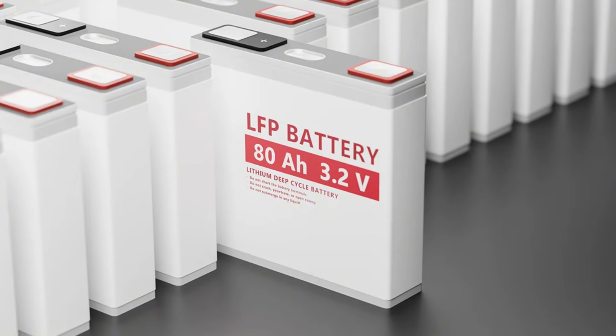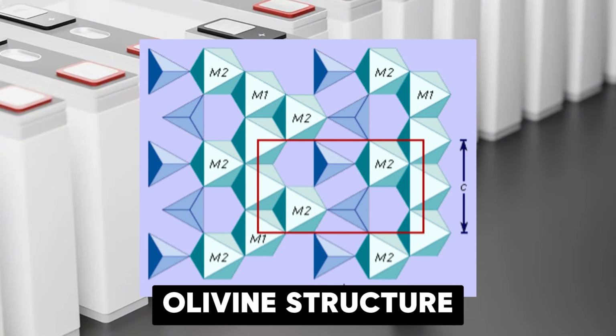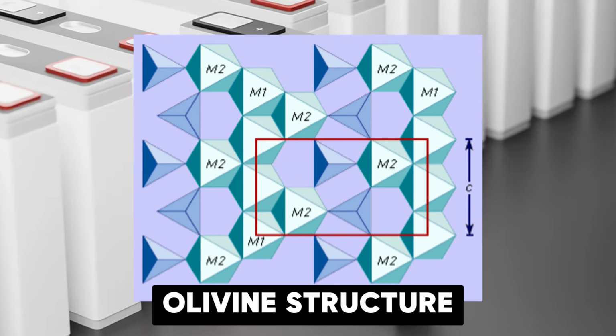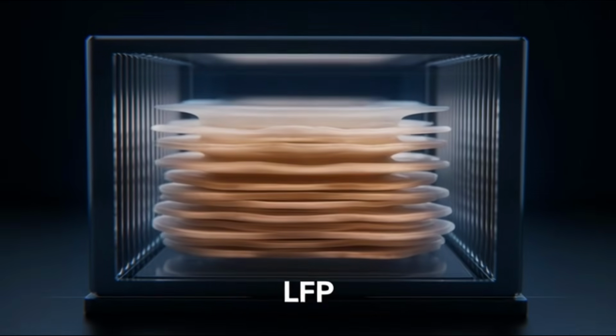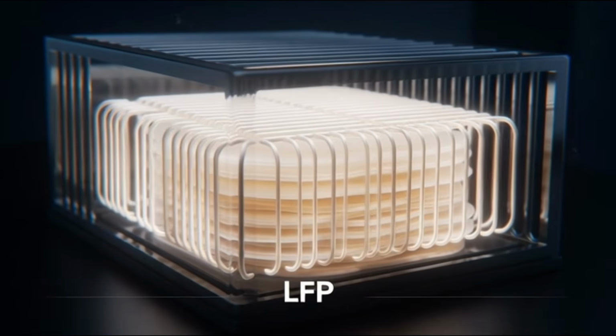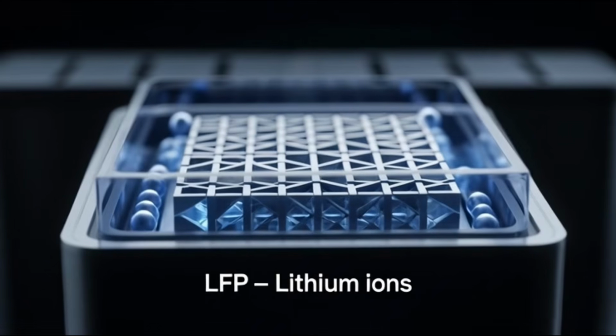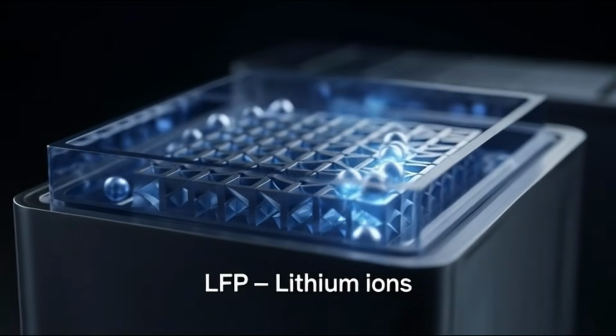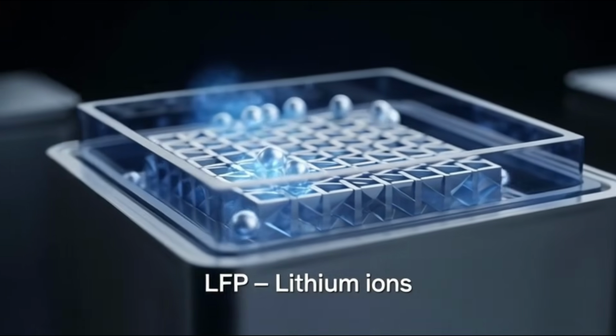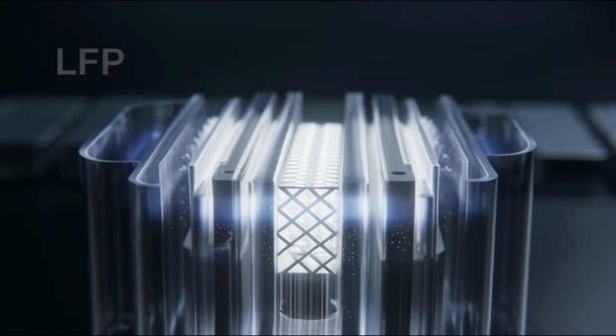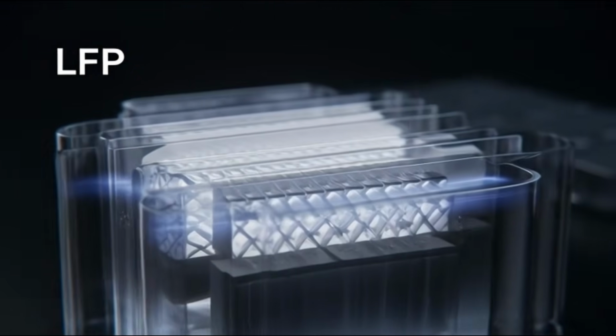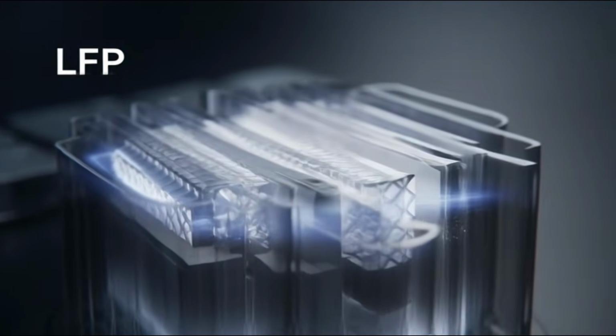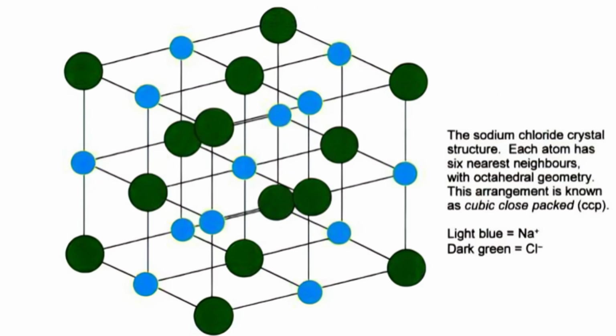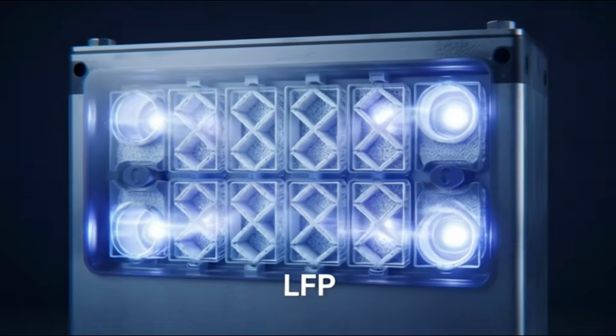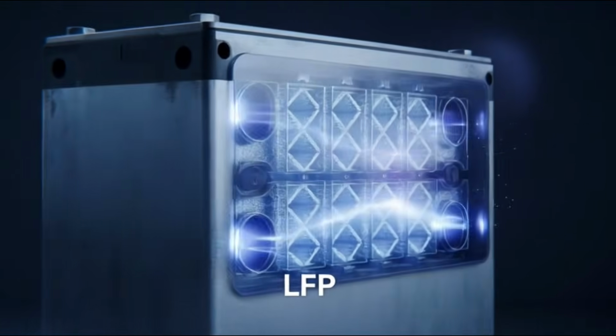LFP, on the other hand, uses an olivine structure, a 3-dimensional crystalline framework. Think of it like a rigid, reinforced cage rather than a flimsy stack of pancakes. When lithium ions flow in and out of an LFP cathode, the structure barely changes shape at all. It's rock solid. Cycle after cycle after cycle, the cage holds. This single difference in crystal geometry is foundational to why LFP batteries survive so many more charge cycles without significant capacity loss.